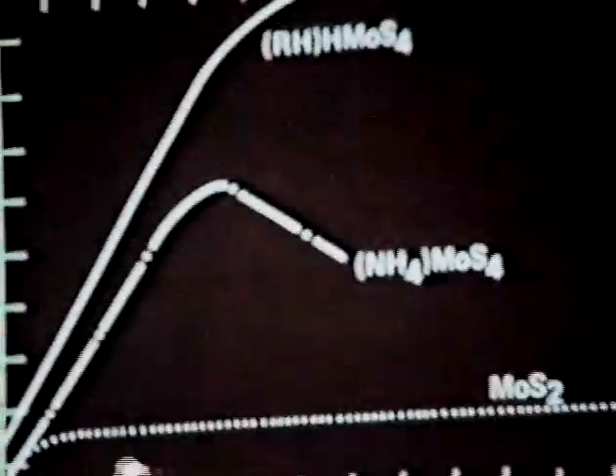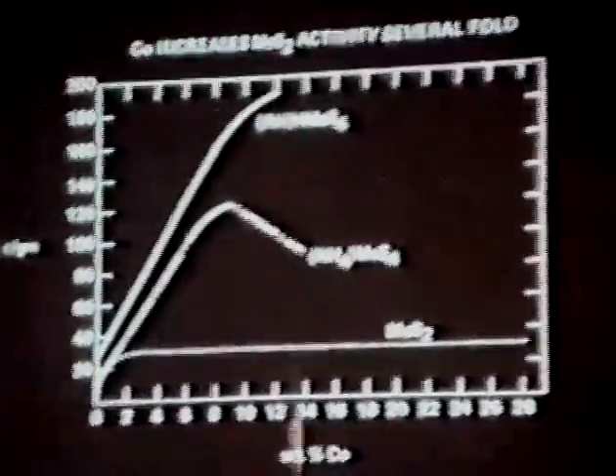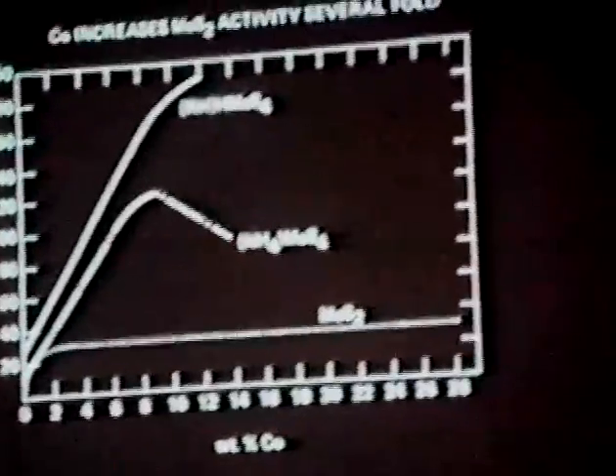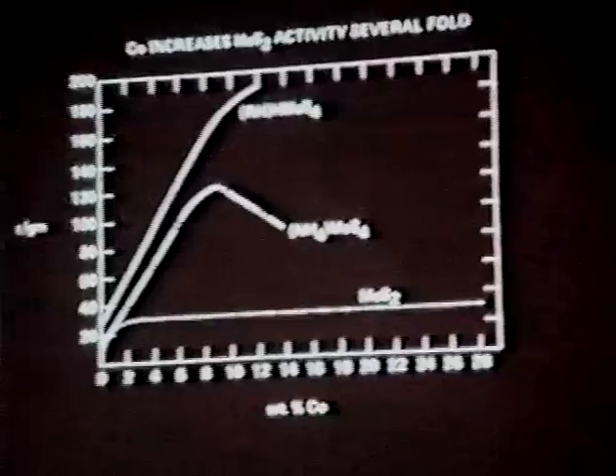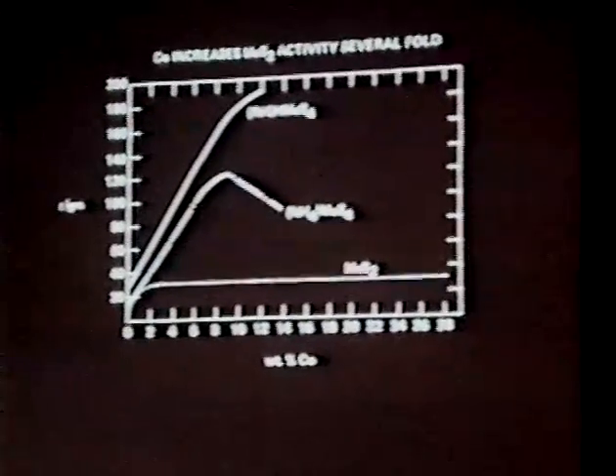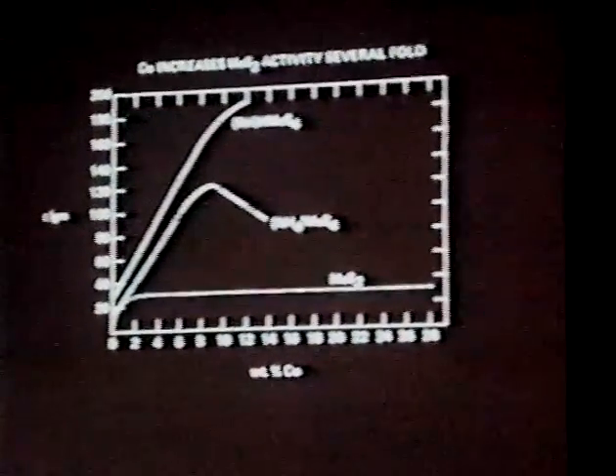So this is a picture which seems to me to bind at least some of the theories in the literature together. If you're above this curve, this point, let's say over here or here in this particular case, you're going to see, if you X-ray or analyze it, a lot of cobalt 9S8. If you're down in this area, you're not going to see much, and here's where we get into the controversy about what that stable state of cobalt is that interacts with the edge.